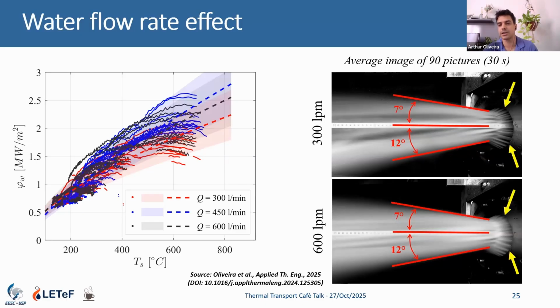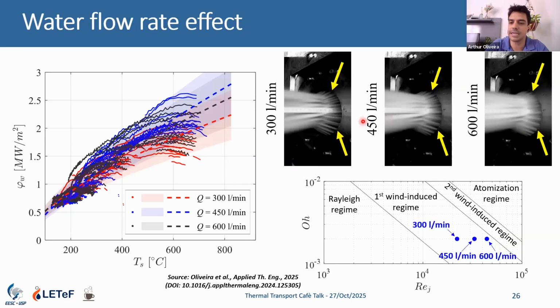What we realized is we have a difference here at the nozzle. When you compare the three conditions, we can see a kind of fog near the nozzle for 600 liters per minute, so we're starting to have some atomization here, which was confirmed when we put that in the Ohnesorge diagram - we are getting closer to the atomization regime.